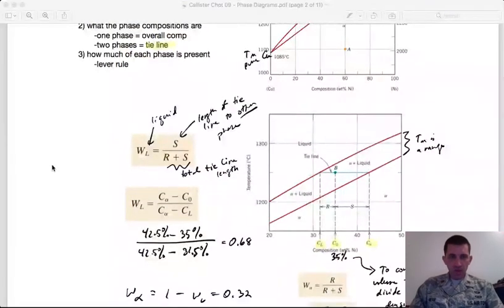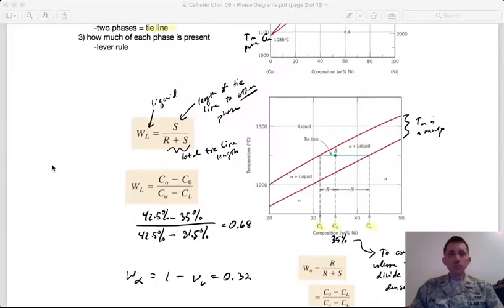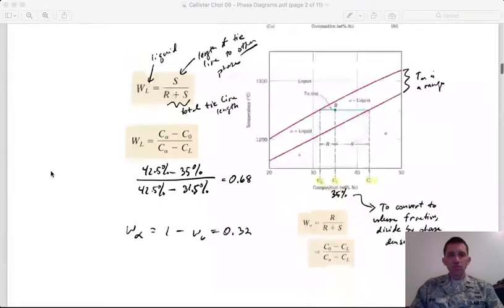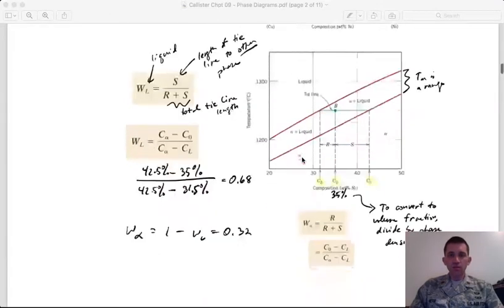I guess we'll cover it right now. Okay, so generally, we use these tie lines to determine the composition of different phases. And we use a rule referred to as the lever rule, right? So here's an example from the nickel-copper phase diagram shown above. Kind of zoom in on this portion between 20 and 50% nickel. And if we are in the region here where we have alpha phase and liquid that are stable together, let's say we are at a composition that looks like about 35 weight percent. So as we're cooling down, when we cross the liquidus, we will start to solidify some alpha. And to determine what the composition of that alpha is, you use a tie line that ties together these boundary lines. And then you can use that tie line to estimate what the composition would be of the alpha phase forming, and then the composition of the remaining liquid.